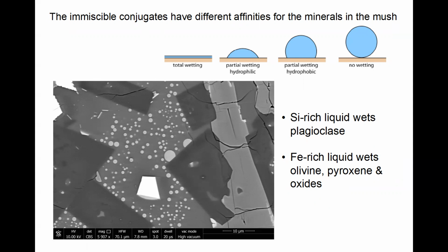So we've got these two liquids, and they've got affinities for different components of the mush. Silica-rich liquid wants to be near plagioclase. Iron-rich liquid wants to be near the mafic phases. So there's going to be some kind of positive feedback there, particularly because the silica-rich liquid crystallizes predominantly plagioclase. So it crystallizes more of what it wants, whereas the iron-rich liquid crystallizes very little plagioclase and mostly crystallizes mafic phases and oxides. So we've got a positive feedback there.